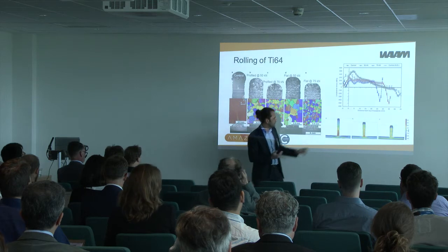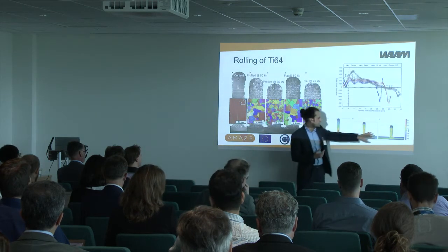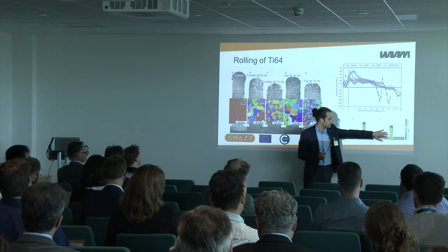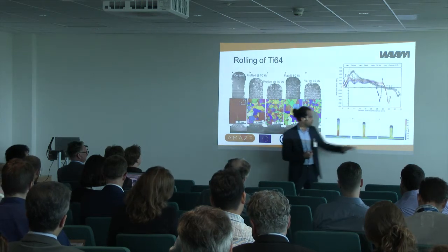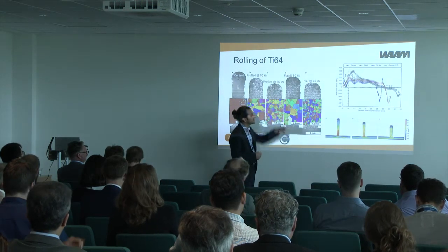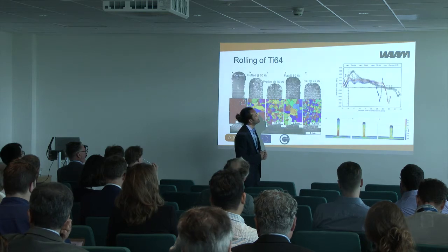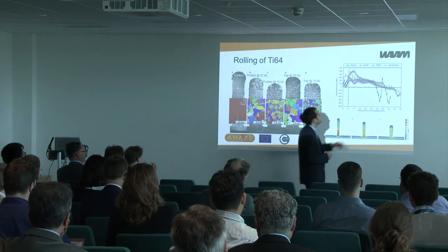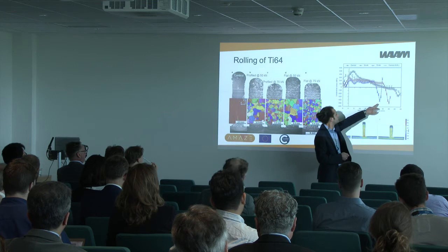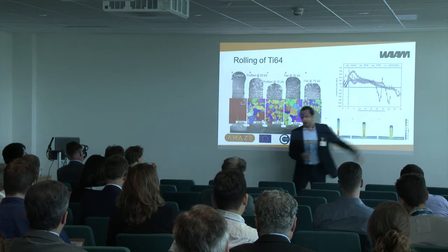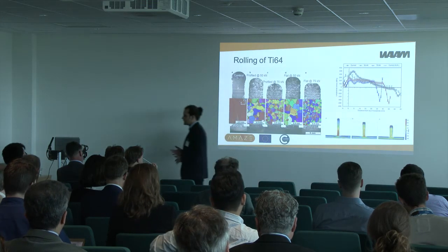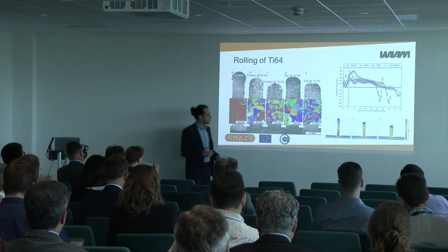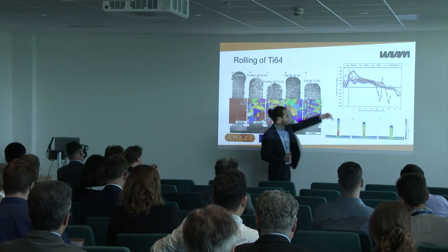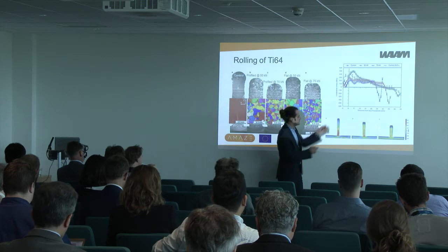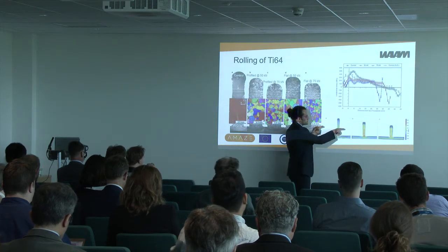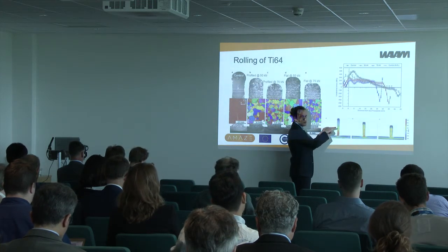And you can see that as we increase the rolling load, the tensile stress becomes gradually lower and much closer to a neutral state. Nevertheless, as you can see from that chart up there, even when we are doing rolling, with the 50 and 75 kilonewton, stresses are still there. That's because, differently from welding, if you are rolling an additive manufacturing structure, when you are deforming the structure from the top, there isn't so much constraint in this direction. Therefore, that's where most of the deformation happens.